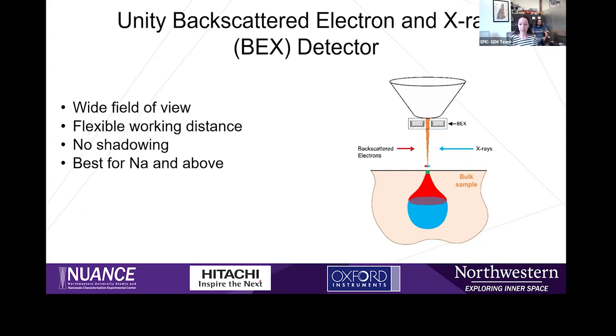Because of its location under the pole piece, the X-ray detector can get exposed to a lot of BSE electrons, so it has special filters for that. An unfortunate consequence of this is it's really best suited if you're interested in elements more massive than sodium. If you're interested in elements like oxygen or carbon, which I don't know why you would have reasons to care about those, kidding, you may need to compare the performance with the other detectors to see if they might be more appropriate for what you're trying to figure out.